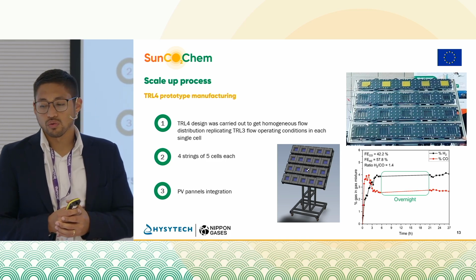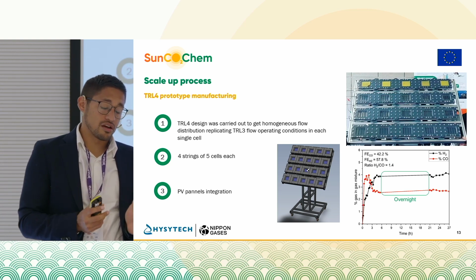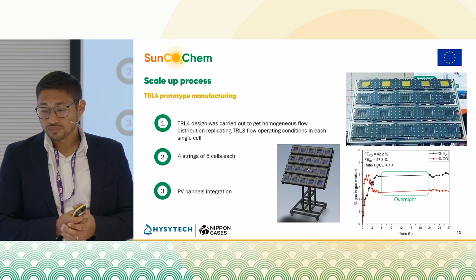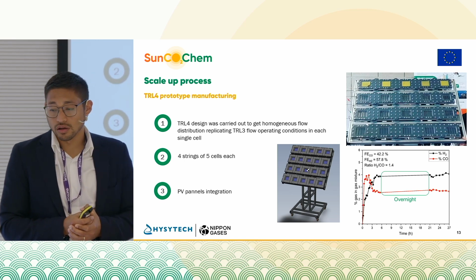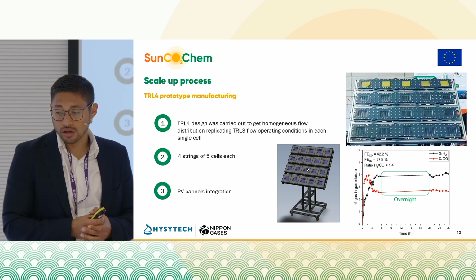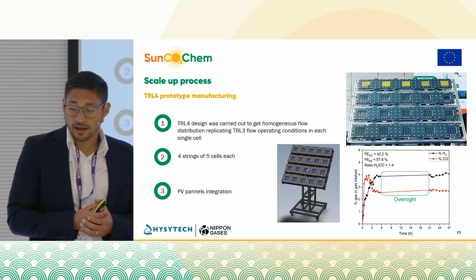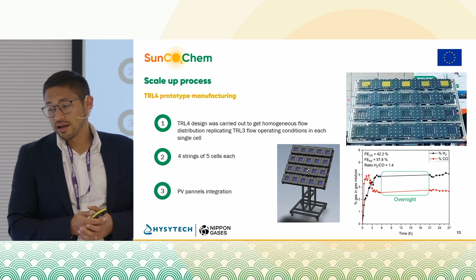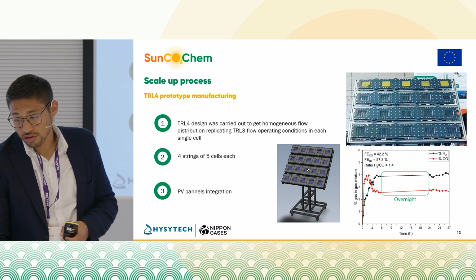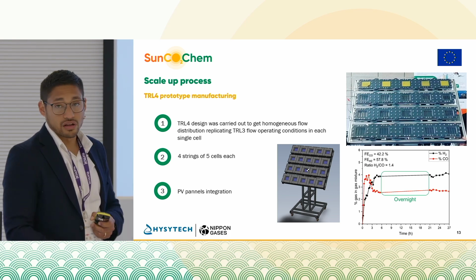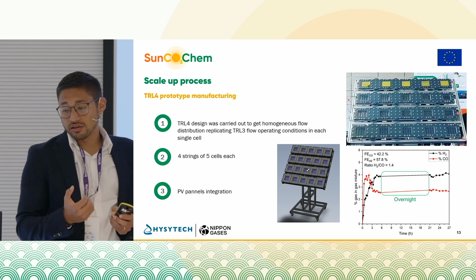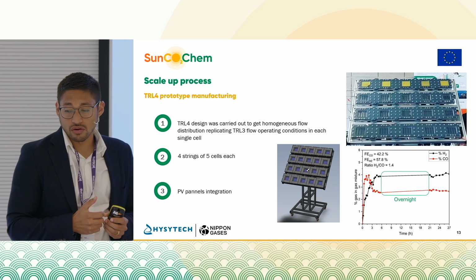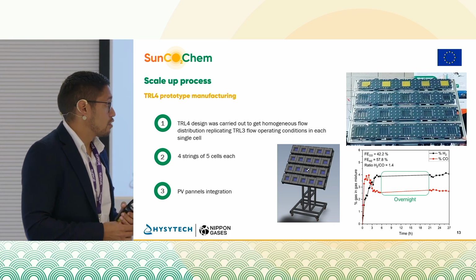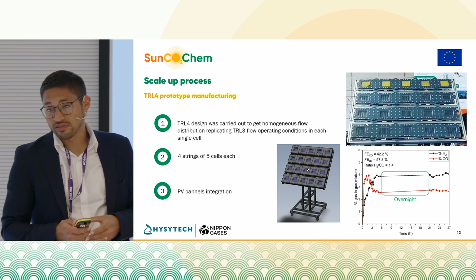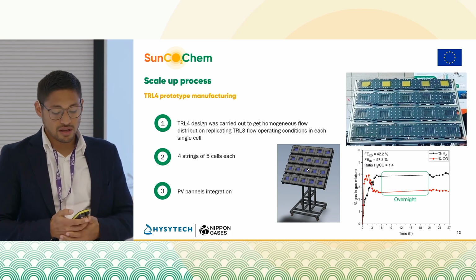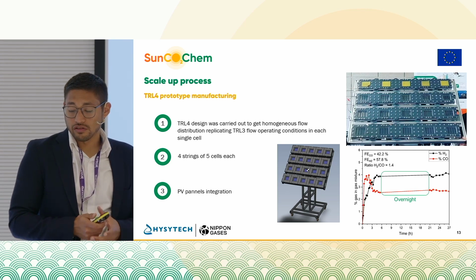The same was done then for the TRL4 prototype, where we passed from 1 cell to 20 cells distributed in 4 strings of 5 cells each, with the integration of the PV panels for feeding the electricity to the device. In this case we also obtained very interesting results, though the ratio of H2 to CO was changed. Anyhow, this was also tested in the laboratory for the hydroformylation reaction, and there were no important changes in the selectivity and the conversion of the raw material towards the oxo products.